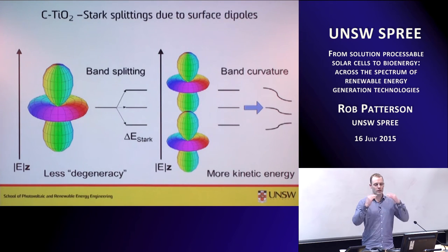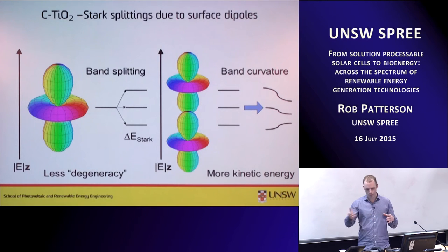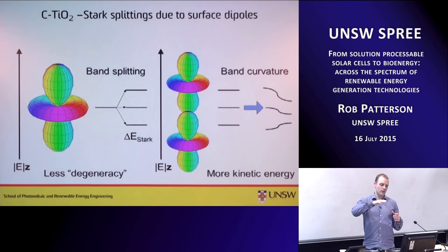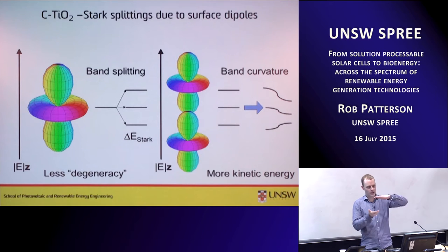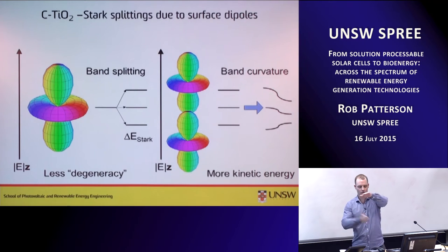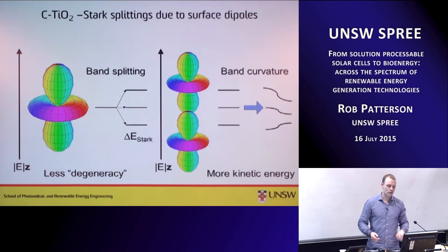So if you have a material that has a band gap and you have a conduction band and you apply a strong electric field to that band, what you see are the splittings. And so one state will go up, one state will go down. And the state that goes down goes into the band gap, you end up with some narrowing. Also, you have some curvature. So if you have a superlattice of these nanoparticles, you can have transport, you can have curvature in your bands. And when you have a strong surface dipole, that curvature increases. So you can also see narrowing of the band gap as a result of not having a flat band. Instead, you have a curved band. And the same thing happens in the valence band. So this seems like a reasonable explanation.